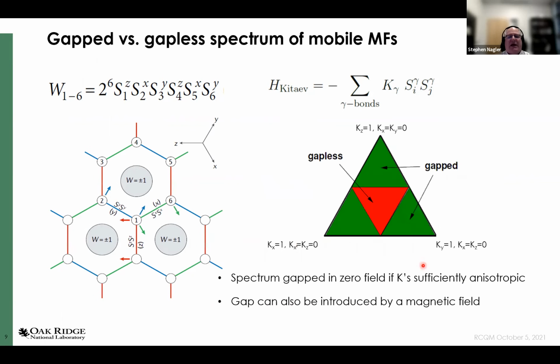Okay. Now, depending on the relative ratios of the constant K sub gamma, which we'll call the Kitaev interaction constant, which can be in the X, Y, or Z direction, if these things are close together, then you have a gapless spectrum for the mobile Majorana fermion. And if one of them exceeds the sum of the others, you'll have a gapped spectrum. Okay, and this is in zero field. You can also introduce a gap by a magnetic field. So it can be gapped by anisotropic interactions or by a magnetic field.